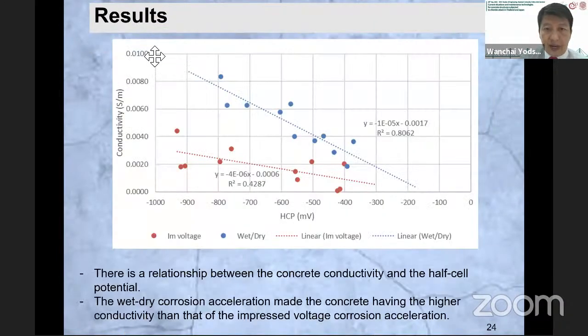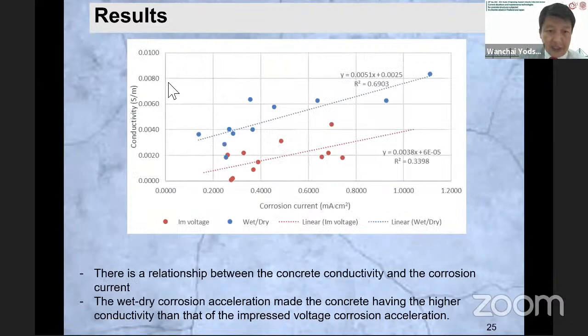And for the result, the first one is the relationship between the conductivity and the half-cell potential. So we can see the relationship between the concrete conductivity and the half-cell potential. And if we compare the wet-dry corrosion acceleration and the impressed voltage, we can see that the wet-dry corrosion acceleration made the concrete have higher conductivity than the impressed voltage method. For the relationship between the conductivity and corrosion current, we have the relationship between concrete conductivity and the corrosion current. And if we compare the wet-dry cycle method and the impressed current method, we can see that the wet-dry corrosion acceleration made the concrete have higher conductivity than the impressed voltage corrosion acceleration.